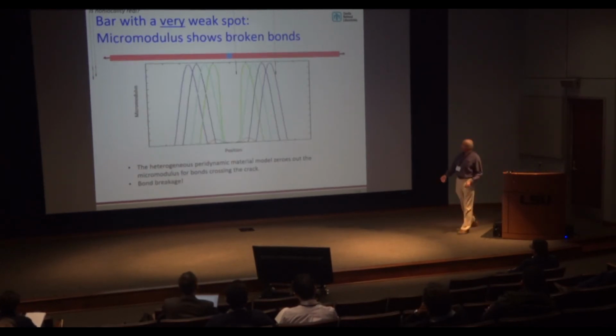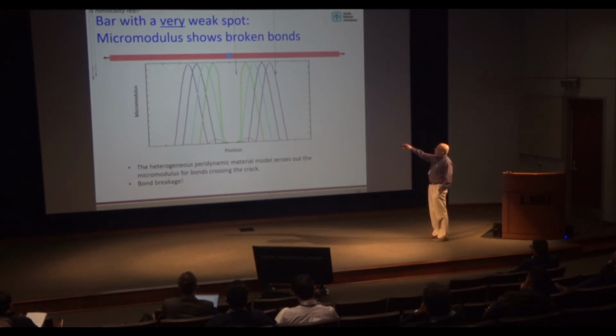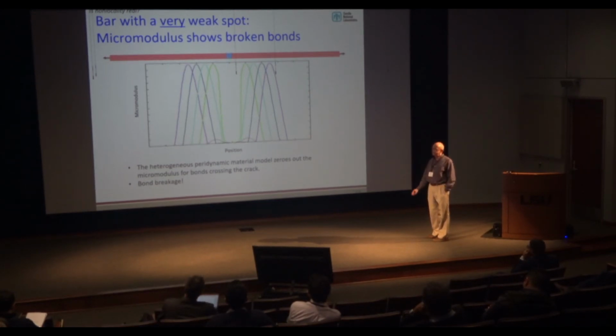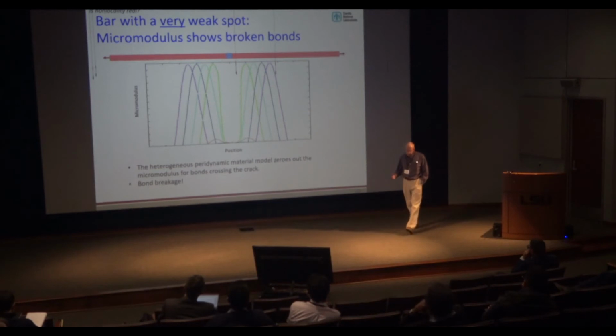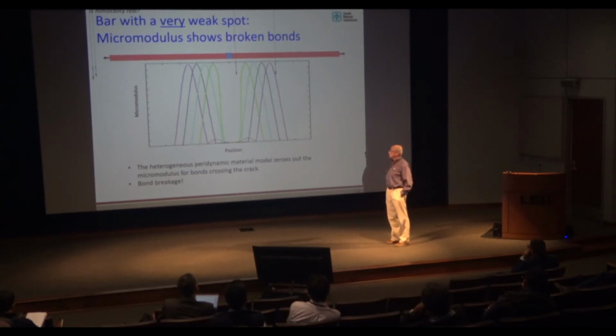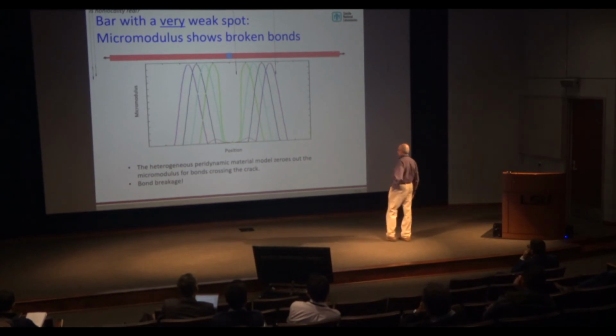But the real reason I'm showing all this is this. If we make the soft spot very, very soft, not quite zero, and repeat that calculation of the micromodulus, which is a function of position, and graph all these micromodulus curves, what you find is that bonds that go from one side of this very, very weak spot to the other have their micromodulus zeroed out. So I claim that that is essentially bond breakage. So conceptually, the point of all this is people say, well, you're arbitrarily assuming bond breakage as your damage model. Where does that come from? So this is one way of looking at where bond breakage comes from.